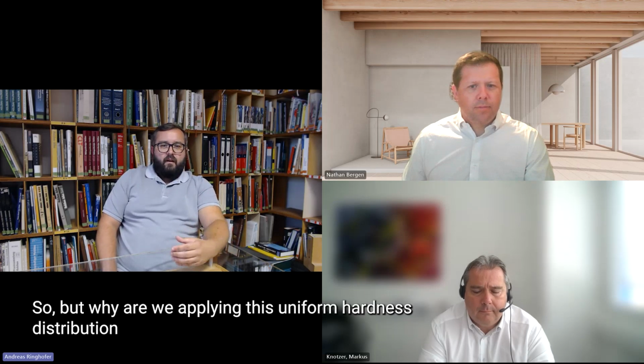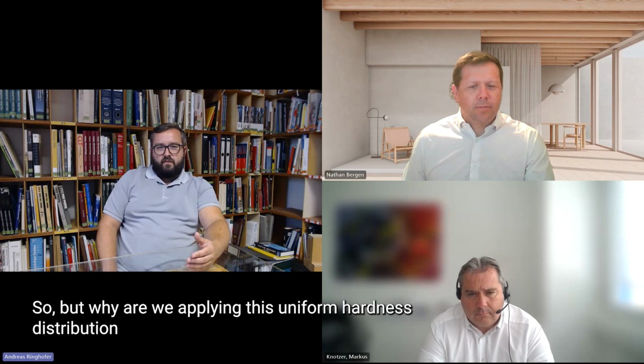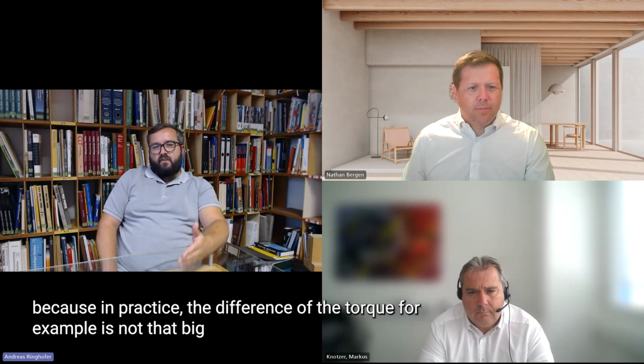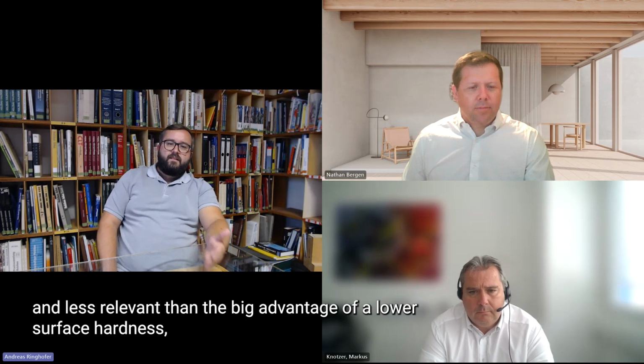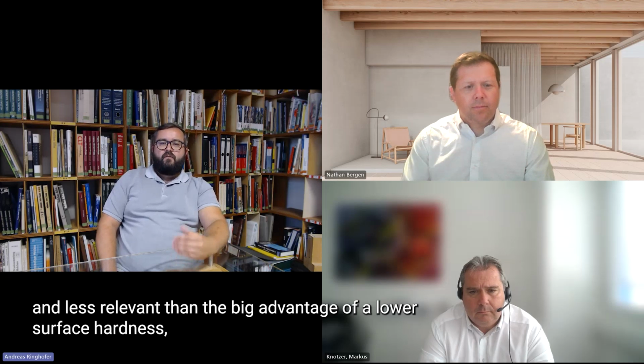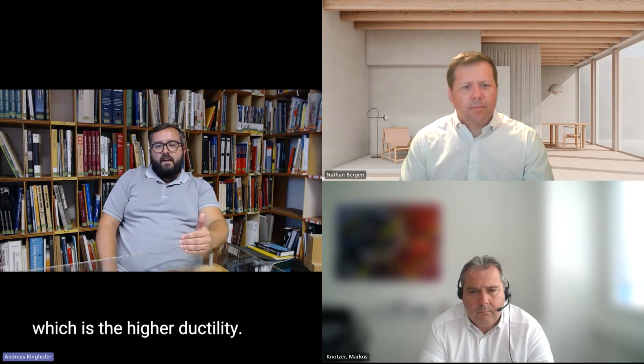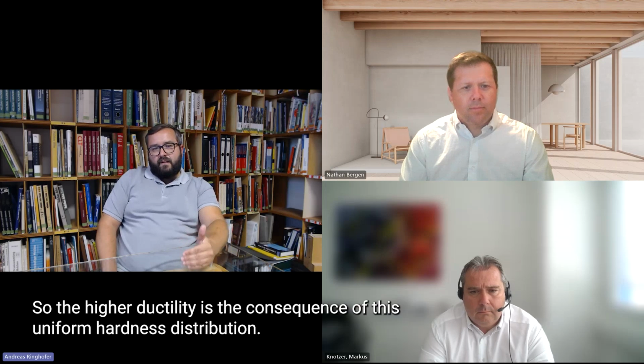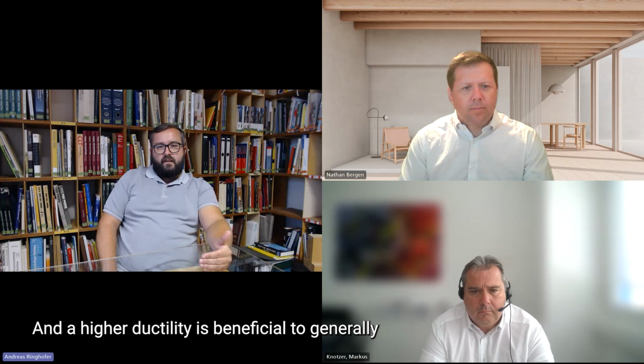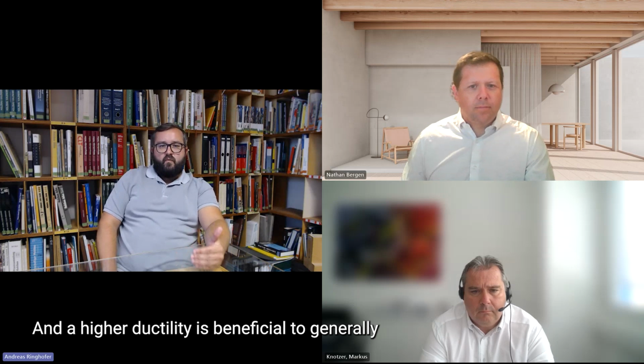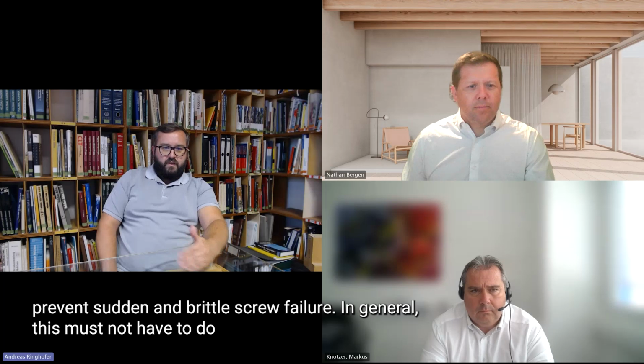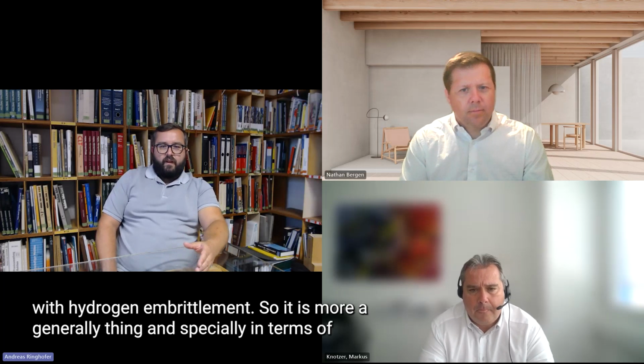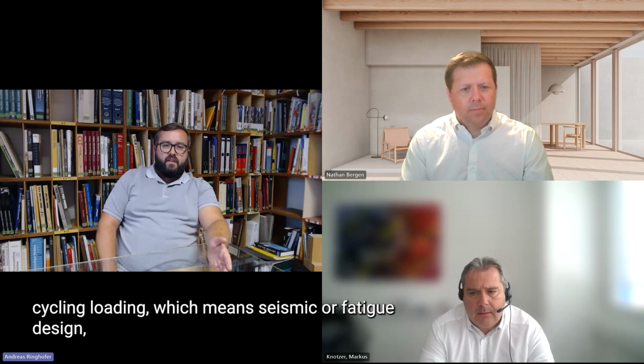So, but why are we applying this uniform hardness distribution? Because in practice, the difference of the torque, for example, is not that big and less relevant than the big advantage of a lower surface hardness, which is the higher ductility. So the higher ductility is the consequence of this uniform hardness distribution. And the higher ductility is beneficial to generally prevent sudden and brittle screw failure. This does not have to do with hydrogen embrittlement, so it's a more general thing, and especially in terms of cyclic loading, which means seismic or fatigue design.